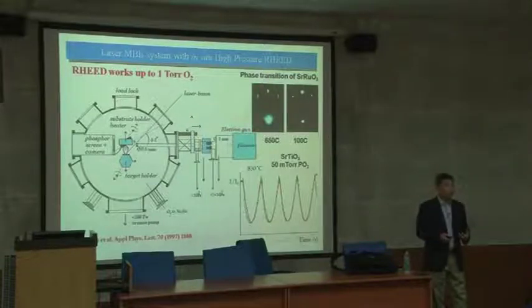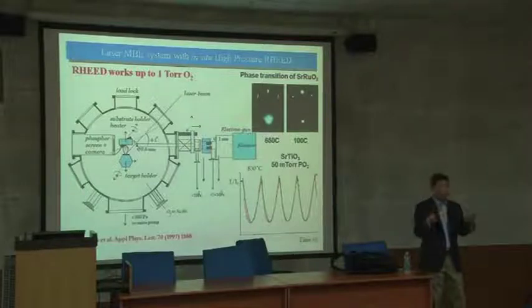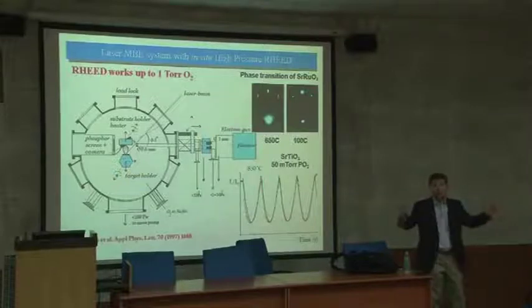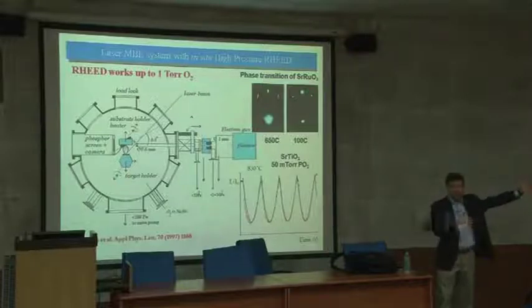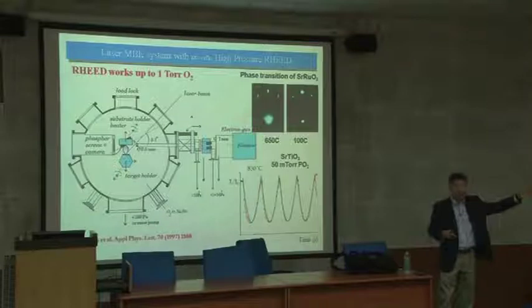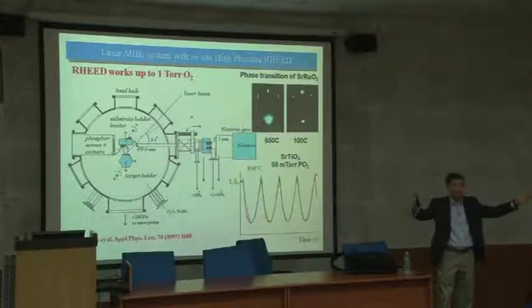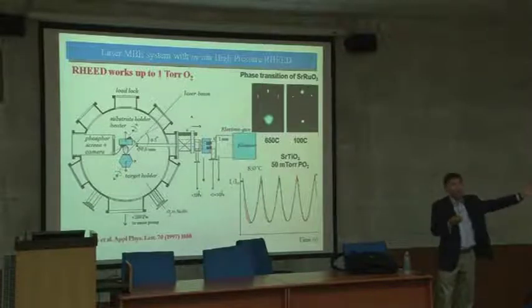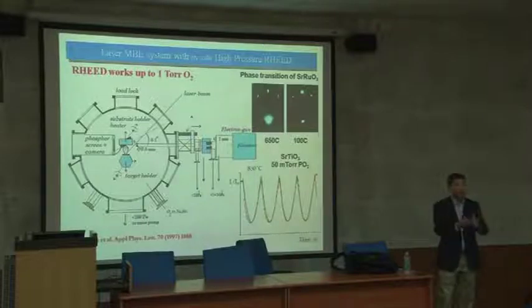And another problem here, you have a lot of oxygen here. Then oxygen gas molecules actually scatter your electron beams. So that means the mean free path of the electron beam can be very short. The normal RHEED guns work in semiconductors over a very far distance, like from the electron beam to the sample to the imaging plate is a very long distance, and then you can do the image there. But if you have this long distance, it is all scattered, you don't see anything. So in order to do that, you have to make this distance very short. Not like a meter distance, it has to be 5 centimeters or 10 centimeters. It's like a factor of 10 smaller distance to make this image possible.